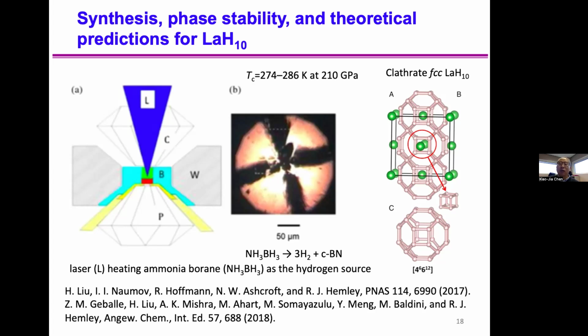Meanwhile, they give you a supporting cubic boron nitride. It's so important. That's why the size is due to the choice of these hydrogen sources. Also, they calculate this TC, which is almost the same as their measurement. A near room temperature superconductor is created.